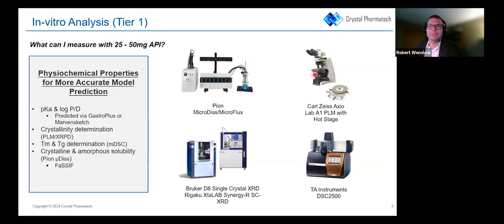One of the things I'm going to have on my grave is, do you have a PLM for that particle? So as I was walking this morning, I realized that Darwin had a microscope way back in the day, and we don't use ours nearly enough. So material that comes in, get a quick microscope image. You could see nice crystals, maybe not nice crystals, amorphous material. It's a really powerful tool, especially with the hot stage.